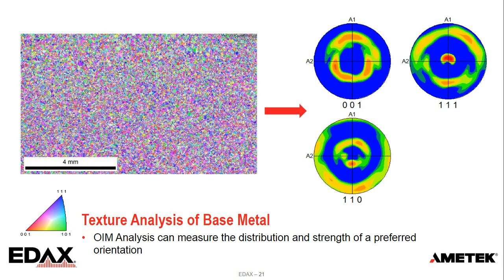And I'm sorry, as I look at this, I realize I didn't put the color scale. But essentially, these colors are on the pole figures, these images on the right, which show the spatial projection of the orientations onto the sample reference frame. The center of the pole figures shows the sample normal direction. A1 shows the top-to-bottom direction, so A1 is the top of the map. A2 is the left-hand side of the map. If you use your right-hand rule, you'll see how that aligns with the map.